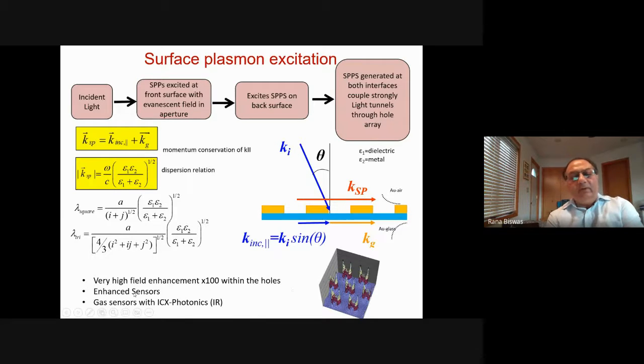So this phenomenon leads to very high field enhancement, more than a factor of 100 within the holes. And in fact, here is a calculation that I have done for the whole array. You can see the field is very high at the boundaries of this hole. And this is for field polarized in the x direction. And this very high field has led to enhanced sensors of various types.